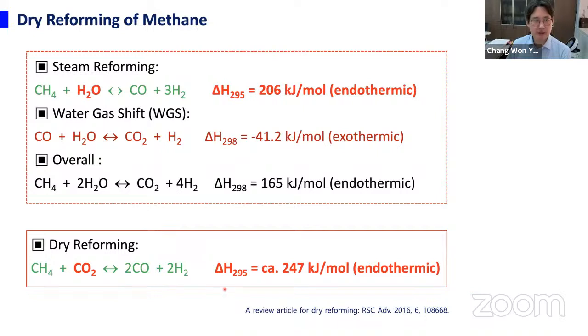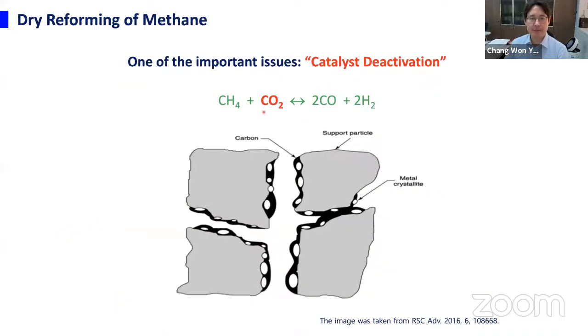One of the issues is, compared with the steam reforming and dry reforming reactions, if you look at the reactant, in the case of dry reforming, the reaction contains more carbon. So one issue that can happen is catalyst deactivation. As the dry reforming reaction goes on, these carbons, upon breaking the CH, CC, and CO bonds, produce carbon that deposits on the surface of this electrode catalyst and deactivates it. That's the problem.